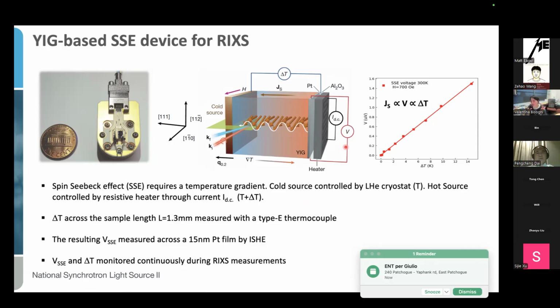Because of geometrical constraints, we could not do it with this device. I cannot change the Q transfer parallel to the magnon current. I see. Because it's a three-dimensional material. So we need to do, and that's what we are planning to, a different geometry and maybe using not spin Seebeck, but another type of magnon current source. And then we can tune Q. So in this very first demonstration, we focus on this plus Q, minus Q.